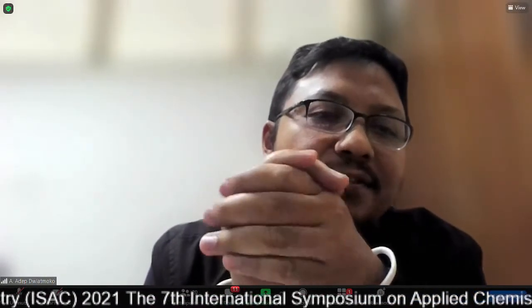And our idea is only to increase the surface of the active site. So if we use bulk molybdenum oxide, it will have only this small surface area of molybdenum oxide. But if we spread it on the surface of activated carbon, which has a very high surface area, we hope that the activity increases much higher. That is our idea. And of course, the support itself, the activated carbon, has some acidity, which also improves the dehydration reaction. And I don't know if this nickel or copper will be active during the reaction or not. I need to look into the literature and some references, and I could not answer the question. I'm really sorry, Dr. Nino.